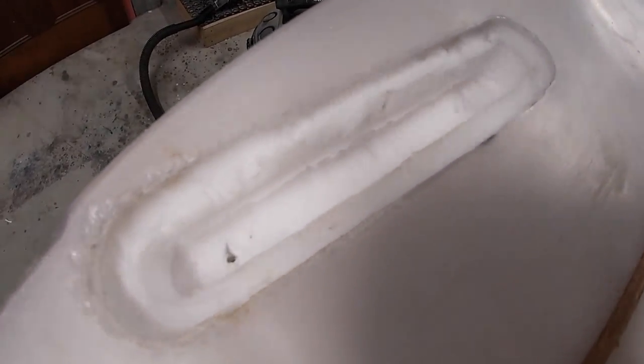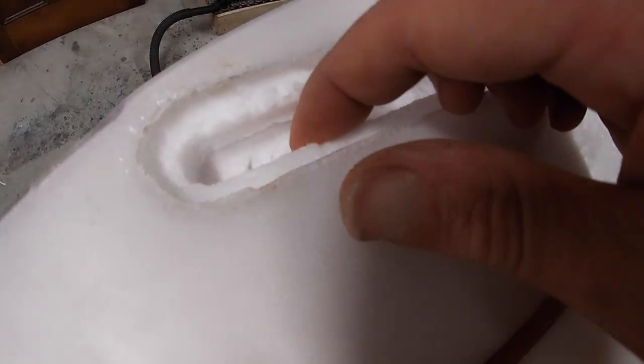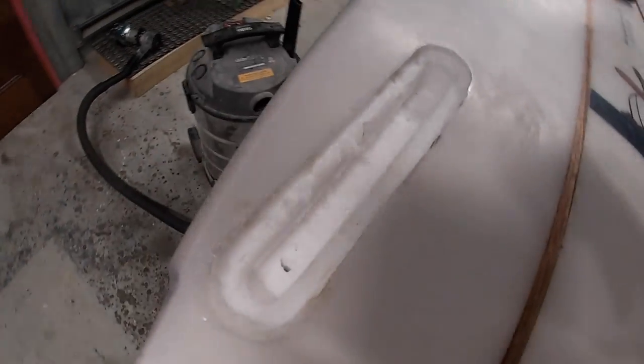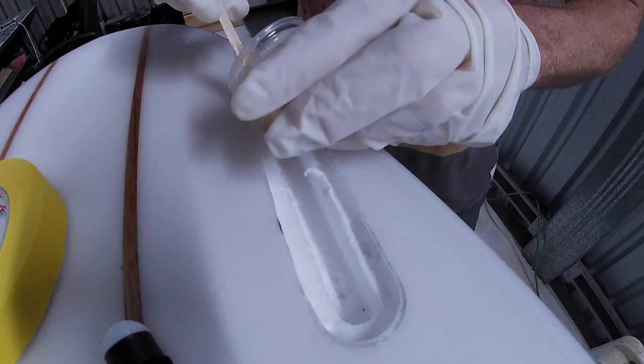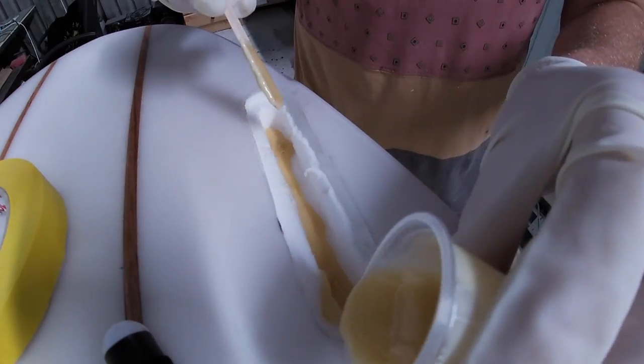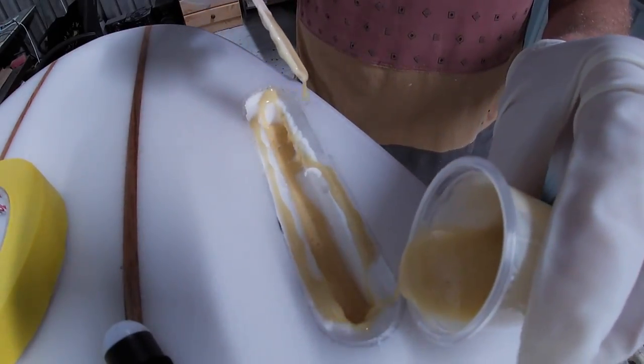All our plastic is out, the box is removed and our fiberglass importantly is still pretty intact. You can see here there's some foam that's kind of dislodged - this is one of the reasons why we don't just fill holes like this with resin. We need to secure this foam so it's not wobbling around, all weak and loose. So I'm going to use this pour foam. If you don't have pour foam then you're going to have to route the shallow area where the flange was sitting to the same depth as the centre of the box where the fin slot was. That way you've got a nice even shape and it's all at the same depth, and then you can cut your foam block out and fix that in there with some resin mixed with some micro balloons.